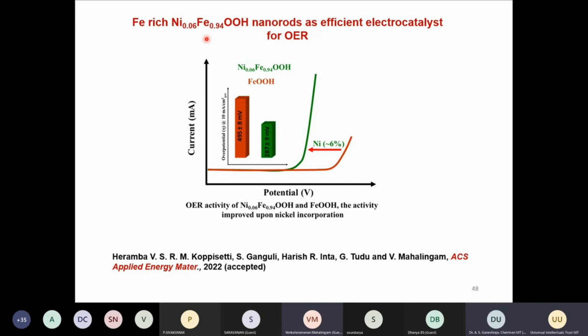However, our idea is, if we do nickel oxyhydroxide, the activity might be better, or cobalt. But the problem is nickel and cobalt, their abundance is very low. We thought, iron-doped materials, iron-doped cobalt, iron-doped nickel, have shown better activity. However, most of the time it's a very small amount of the iron which increases the activity of the sample. So we thought, why don't we make the nickel the other way, whether it will be possible.